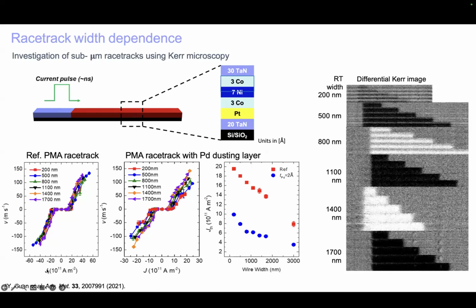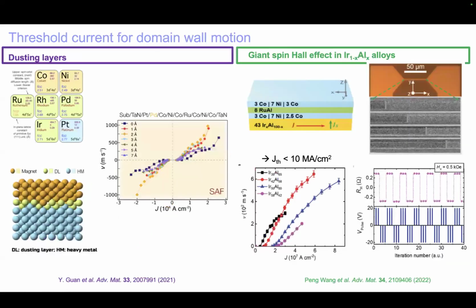And on the left-hand side, you can see a typical velocity of the domain wall as a function of increasing current density. At low current densities, the domain walls don't move. There's a threshold current density above which they move, and the velocity increases as we generate more torque from the spin polarized currents. So we were supposed to talk a little bit about materials, and materials are very critically important.